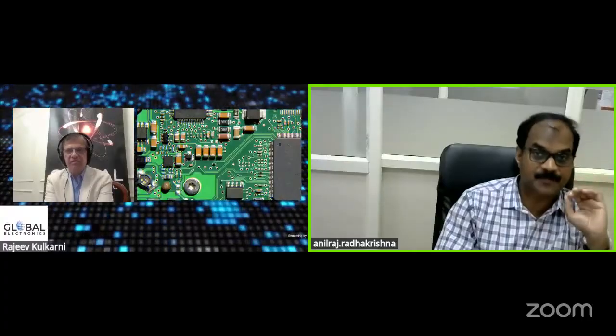The fifth one is a very expensive one, that is parylene coating. Parylene, different types like C, D, F of conformal coating are available. In all other cases, the conformal coating material is applied onto the product, but in this case it is a vapor. So this is applied via vapor phase deposition. Since this is a vapor, a thin layer of coating can be applied. This is very suited for moisture, chemical, and solvent protection.